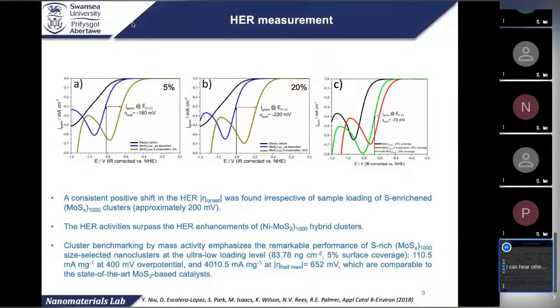Basically we test different materials, which are pure MoS2 and MoS2 plus sulfur, and we test different coverage. We tested 5% surface coverage, which means that 5% of the surface is covered by the cluster, and in figure B, it's 20% of the surface area covered by the cluster.